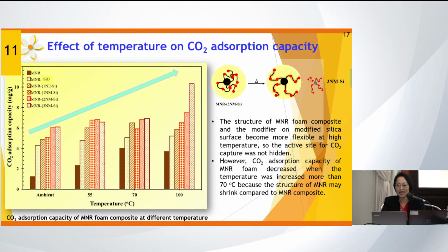However, the carbon dioxide adsorption capacity of the modified natural rubber foam decreases when the temperature is increased to more than 70 degrees Celsius because the structure of the modified natural rubber foam may shrink compared to the modified natural rubber composite.